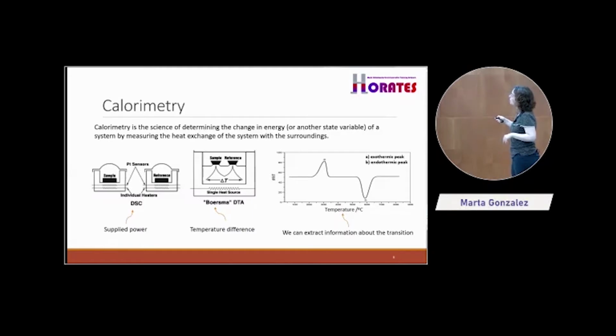Another way of doing calorimetry, this one here, the DTA, differential thermal analysis, is that, again, I have a reference that does nothing. I have a sample that will have some kind of reaction. And what I do here is much simpler. I get less information, but it's much simpler. What I do is provide a certain constant amount of power all the time, and I check whether the temperature is going up or down according to the ramp I'm providing. And so if I have a delay or it advances too fast, I get information about this kind of reactions, okay? But I lose some information here. This is, as I said, a curve with an exothermic peak or an endothermic peak, depending on whether I'm giving more power or stopping giving power.